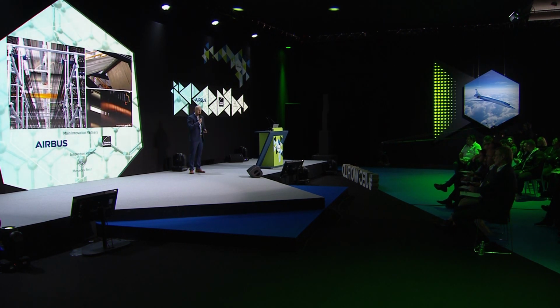In an industrial process, we have several hundreds of fibers which are processed simultaneously, each fiber consisting of thousands of filaments that are processed over a distance longer than 1 kilometer at an average speed of 12 meters per minute. And the problem here is that this complex operation is only monitored manually by a few operators. So it's easy to understand that we have a lot of fiber damage in the process.